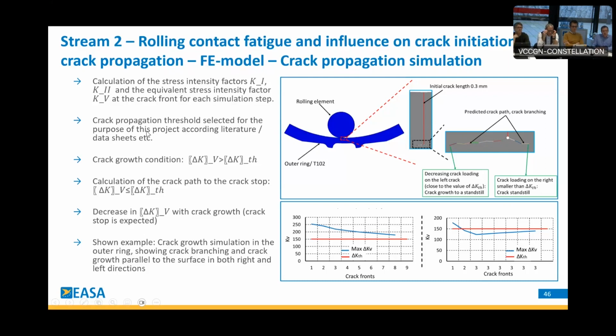The crack propagation threshold that is used here, which is given in the diagram here as the red line, is selected for the purpose of this project according to literature, data sheets, and so on. It was not a target to define it or to challenge it. The crack growth condition is delta K_V larger than delta K_th. If it is growing, then this must be fulfilled. The calculation of the crack path for the crack stop, you see it here, is the opposite. If we see a decrease in the delta KV with the crack growth, the crack stop is expected.